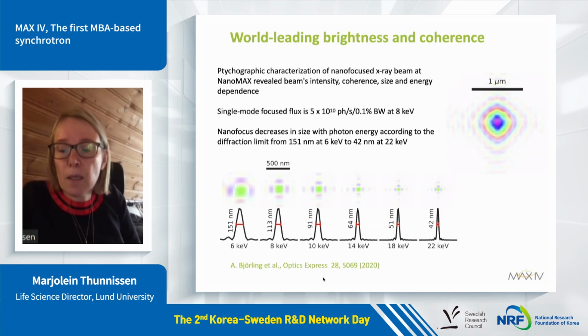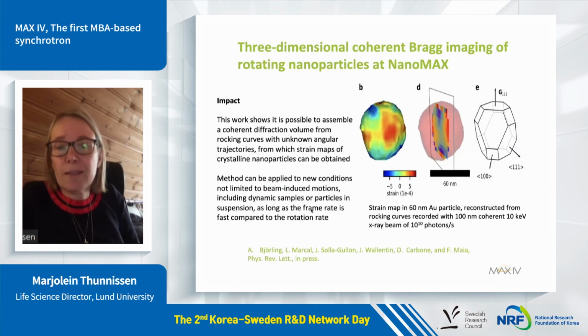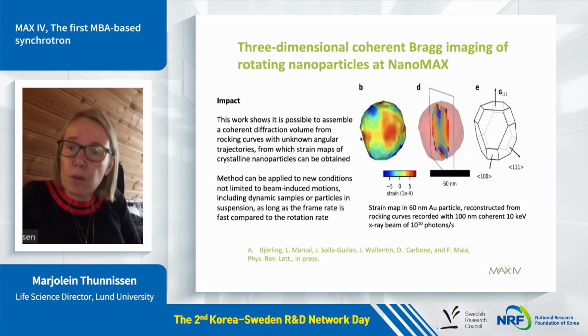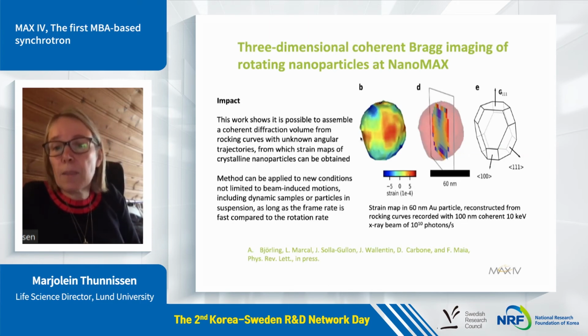And with this high coherence, you can do quite new experiments. So the following experiment is a quite simple one. It's called nanoparticles, which were floating. So in classical crystallography, you have to do rotations. In this case, these particles were floating with their own small rotations. And by using coherent diffractive imaging, we could actually assemble the coherent diffraction volume so that we could show the image of the full rotating nanoparticle.